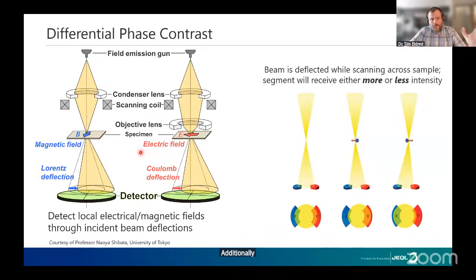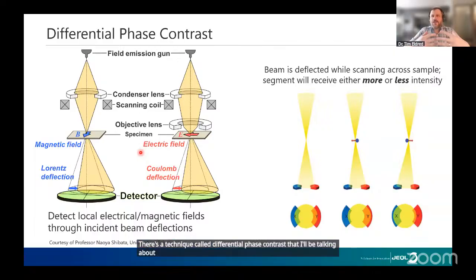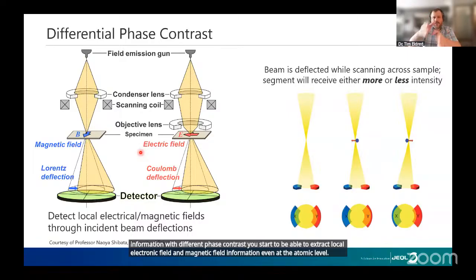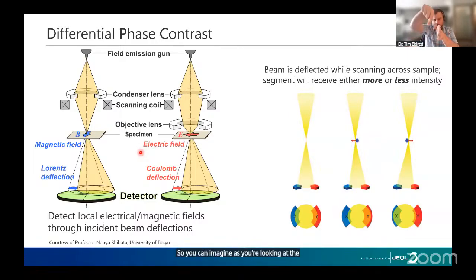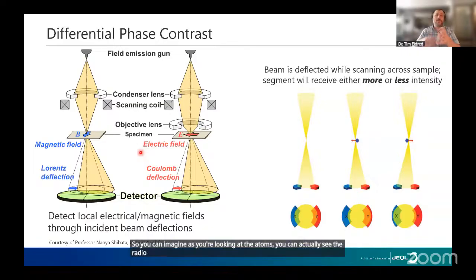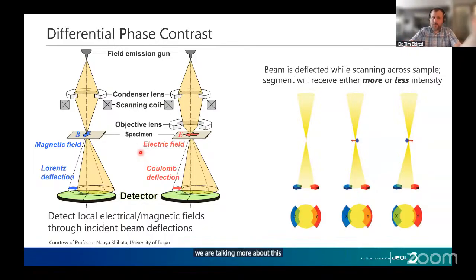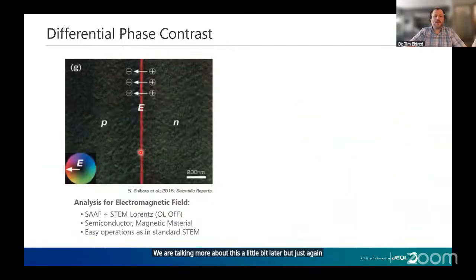Additionally, there's a technique called differential phase contrast that I'll be talking about later. So the images that I showed earlier were ADF, where you get atomic information. With differential phase contrast, you start to be able to extract local electric field and magnetic field information, even at the atomic level. So you can imagine, as you're looking at the atoms, you can actually see the radial electric field coming off of these positions. We'll be talking more about this a little bit later, but again, putting some things out into the open.